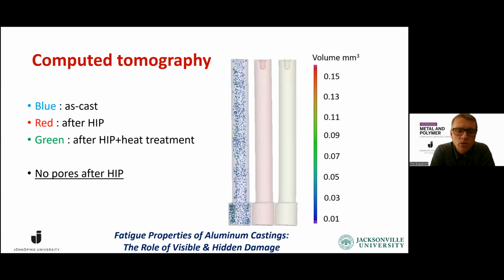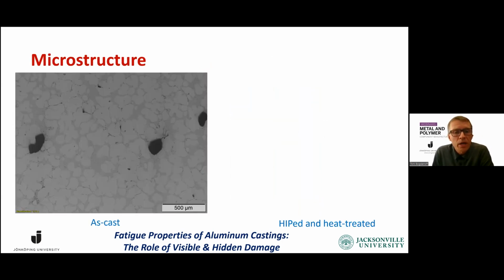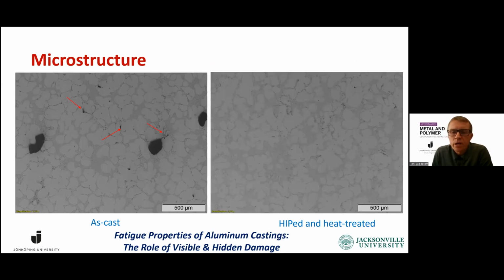So the blue one is in the as-cast condition, and then the red one is after the HIP process, and green is done after the heat treatment after the HIP process, just to validate that no pores are opening up. But what is clear is that there are no pores at all after the hot isostatic pressing. And if we look at the microstructure in the as-cast condition, we see clear pores, and we also see a lot of hidden damage around pores in other places of the material that we can see with the red arrows. We can find them in different places. And if we look at the HIPed and heat-treated materials, we can also find some parts that actually have some damage that we can visibly see with our optical microscope in this case.